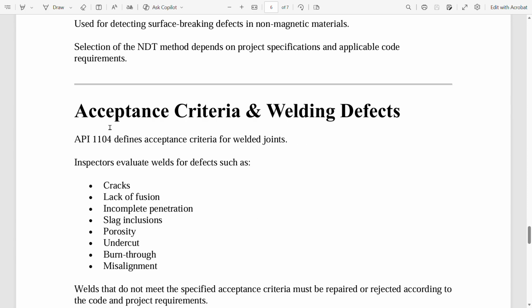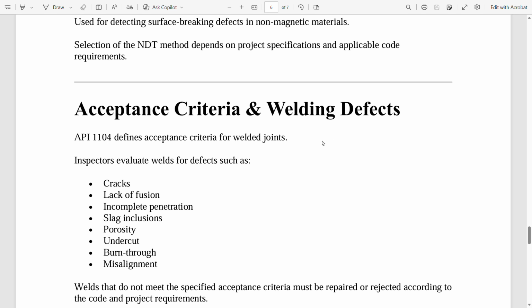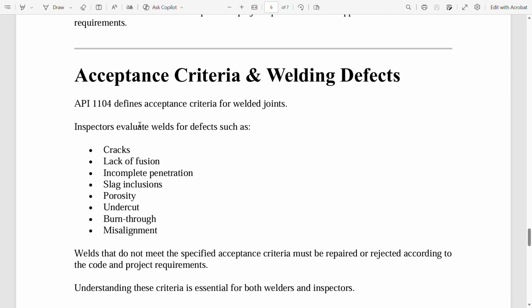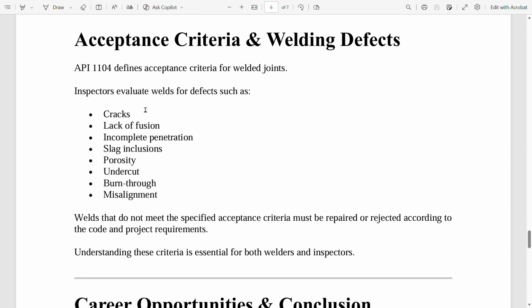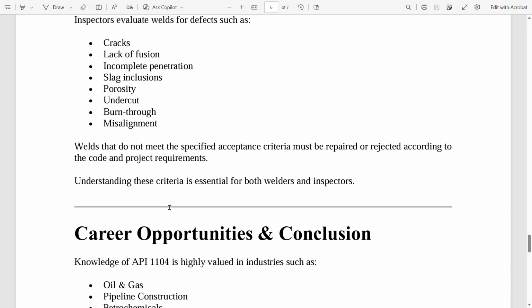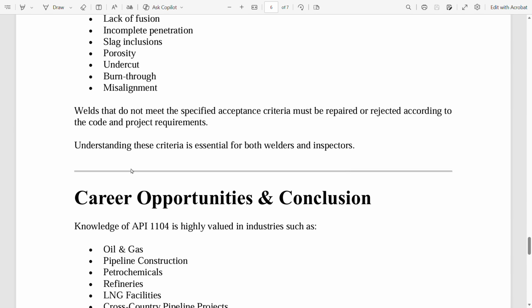Acceptance criteria and welding defects. API 1104 defines acceptance criteria for welded joints. Inspectors evaluate welds for defects such as cracks, lack of fusion, incomplete penetration, slag inclusions, porosity, undercut, burn through, and misalignment. Welds that do not meet the specified acceptance criteria must be repaired or rejected according to the code and project requirements. Understanding these criteria is essential for both welders and inspectors.